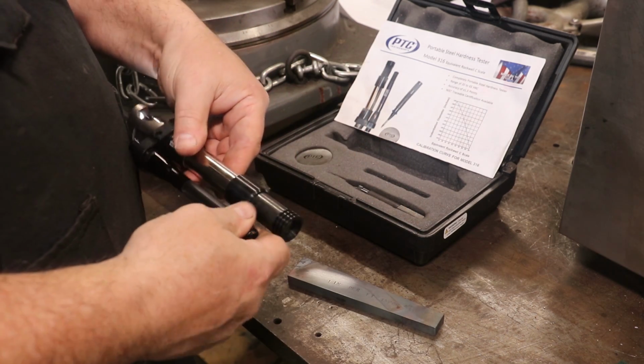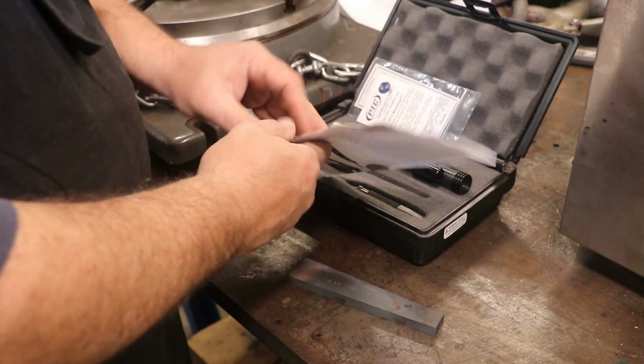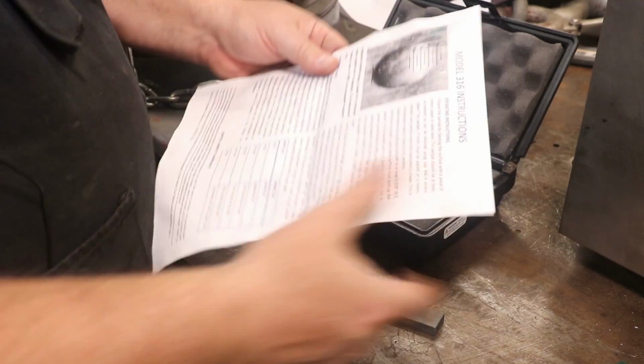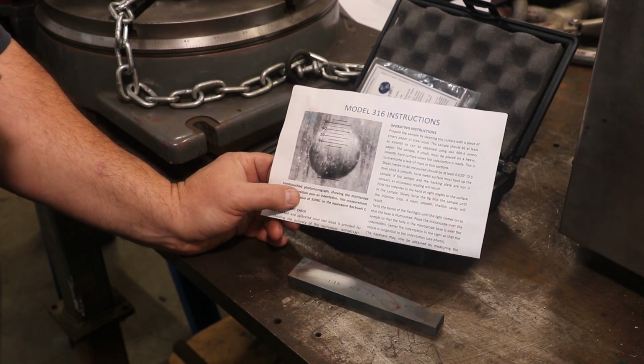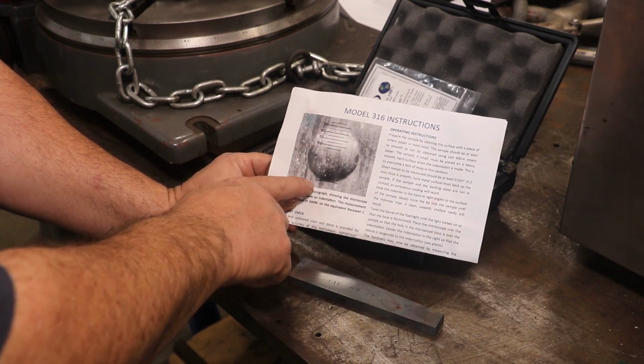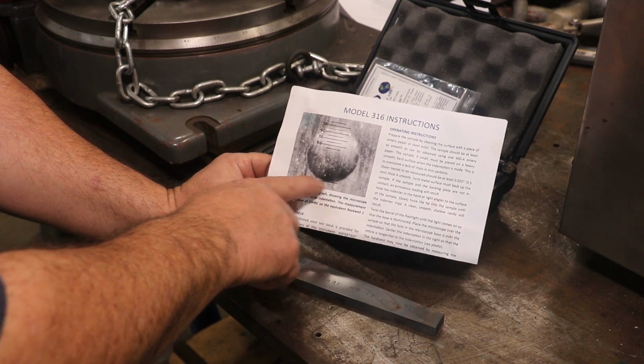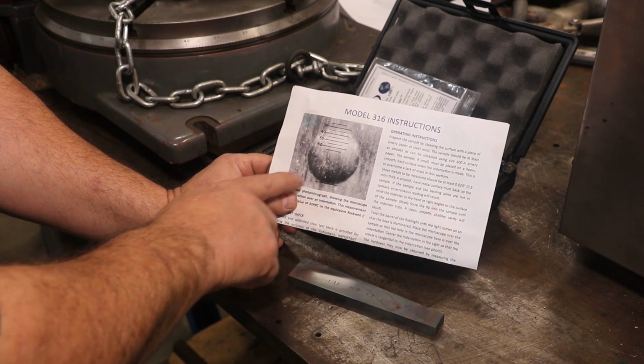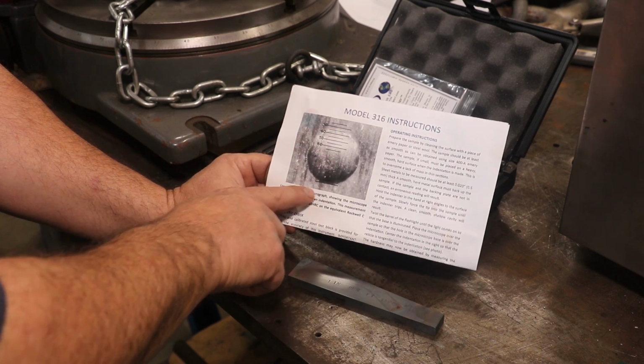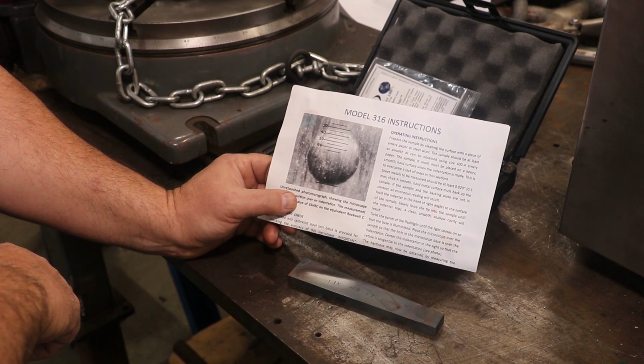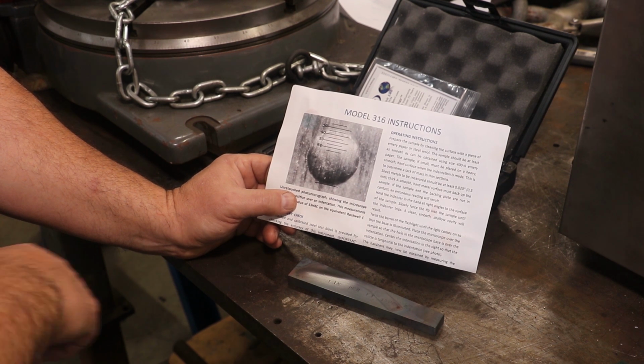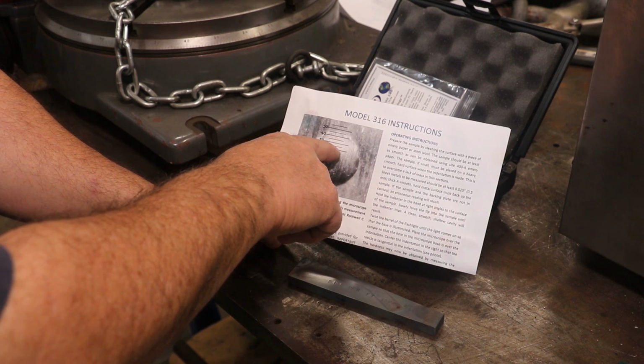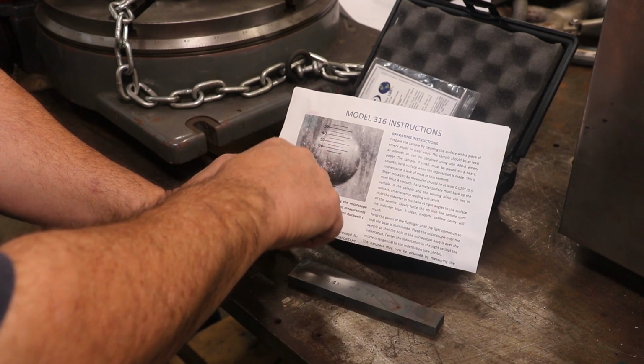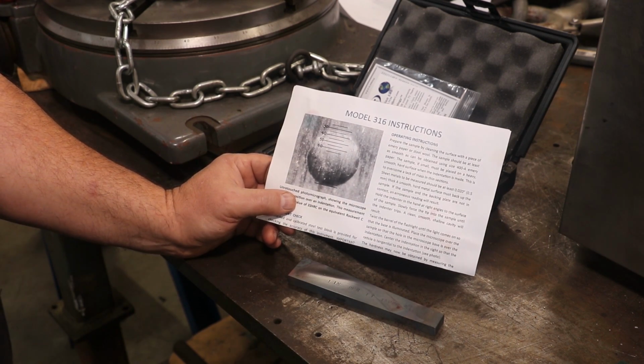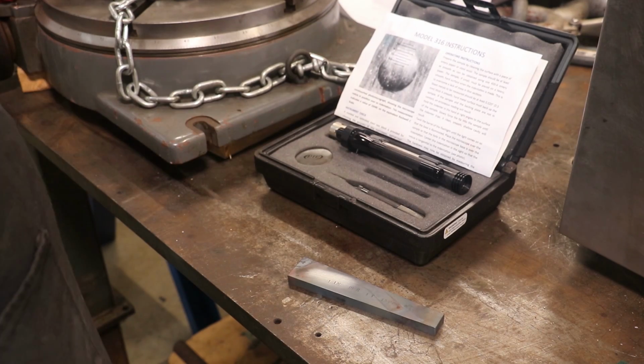I'm estimating there. And to kind of give you an idea of what that looks like, I can't really show you down the viewfinder that I've got, but there's a picture in the instructions, and you just line this up. There's a scale in that little microscope thing. You put the line on the edge of that dot, you can see the indentation, and then you can read on the scale here what the hardness is based on how far that little punch penetrated down in there. So again, my punch is between about 55 and 60, so it's kind of in this range here, much smaller than what you see on the diagram. So anyway, that kind of gives me an idea of what the hardness is.